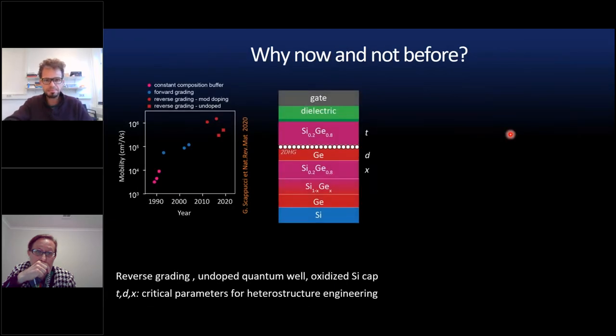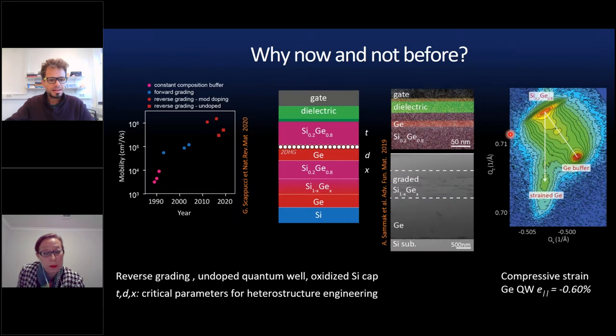So why now and not before? As I said, really this field of using germanium for qubits took off in the past few years after our work with quantum wells. But in reality, these germanium quantum wells have a long history that traces back to the 90s. And from a material perspective, the breakthrough was around 2010, when the mobility of these structures suddenly achieved around 1 million, which put them really on par with high quality III-V materials.